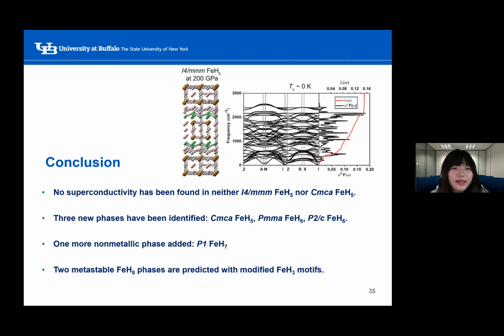So in this study, we found no superconductivity for FeH5, and we identified three new phases, including FeH5 and FeH6. We found one more non-metallic phase, P1 FeH7, and we found two metastable FeH8 phases, both with modified FeH3 motifs.